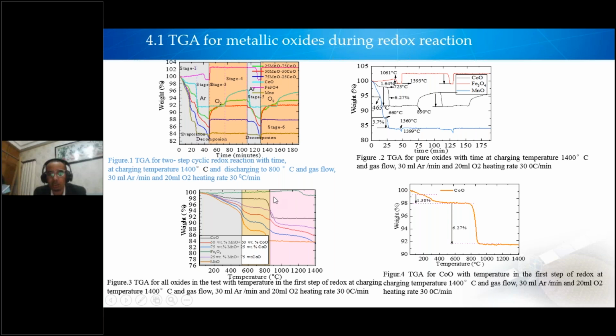So from this, for example for cobalt, charging from room temperature to 1400, we see a single decomposition there. So in cobalt oxide, from this region, the cobalt just goes straight. It needs high temperature to change its phase.